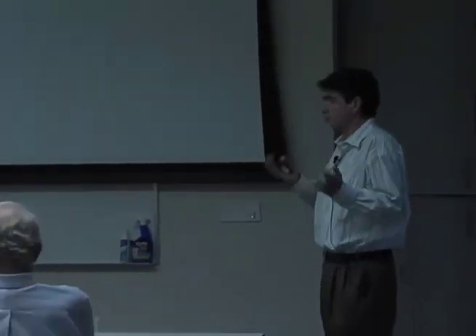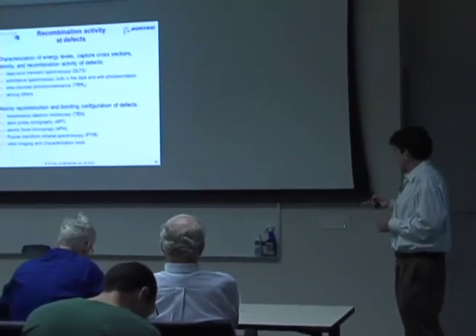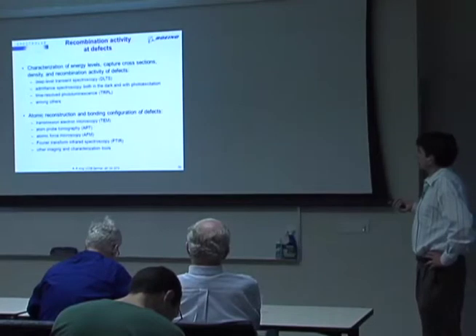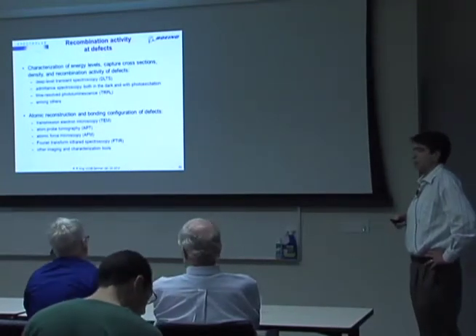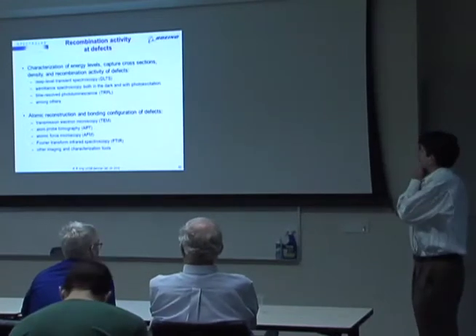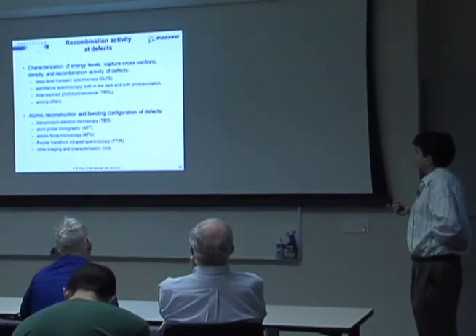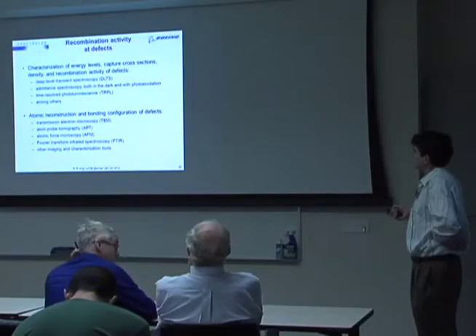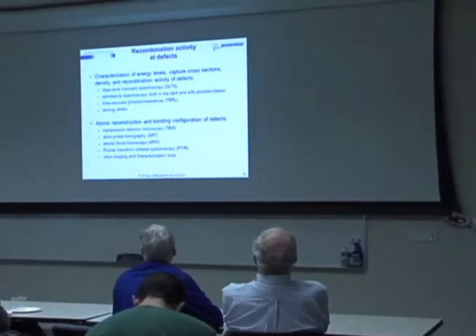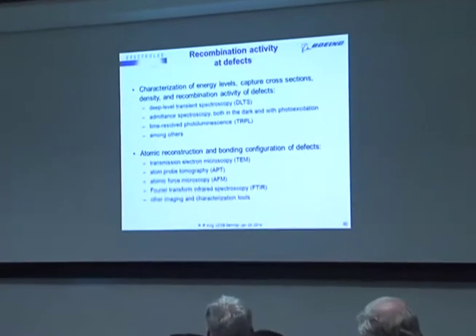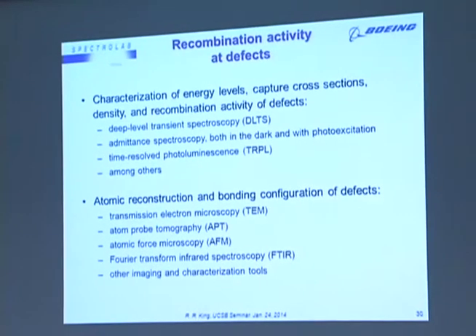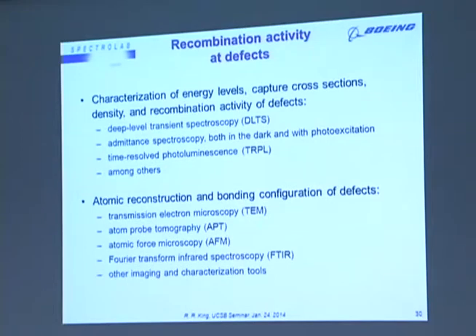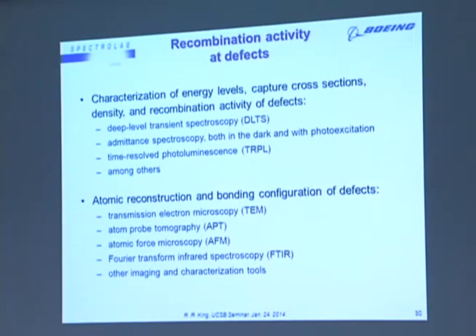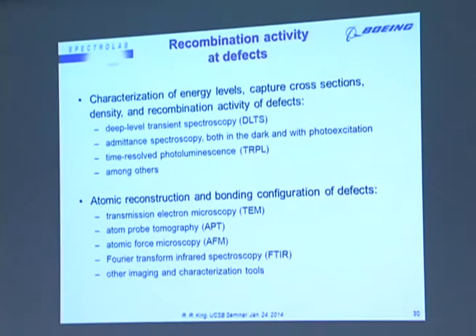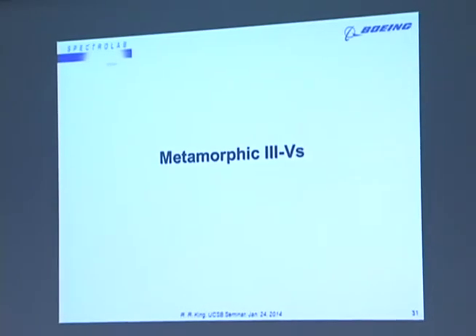So being polycrystalline materials and being materials that are formed in a somewhat non-ideal but also intriguingly low-cost method, these materials can have a high density of dislocations, both extended defects, grain boundaries, and point defects within the grains. So we use a variety of techniques: deep level transient spectroscopy, admittance spectroscopy, both in the light and the dark, and time resolved photoluminescence to measure the lifetime of carriers directly. And also we can get a better idea of the atomic configuration of these defects with techniques such as transmission electron microscopy, atom probe tomography, AFM, and FTIR is quite useful as well for getting to the bottom of what is the actual structure of these defects.